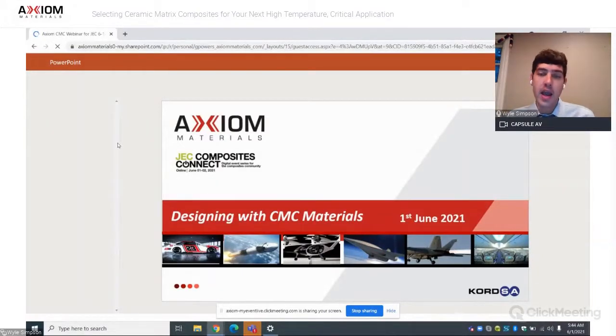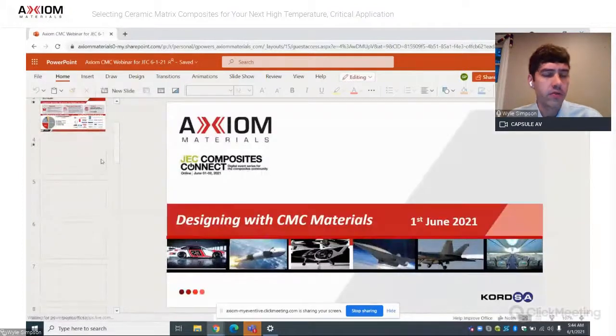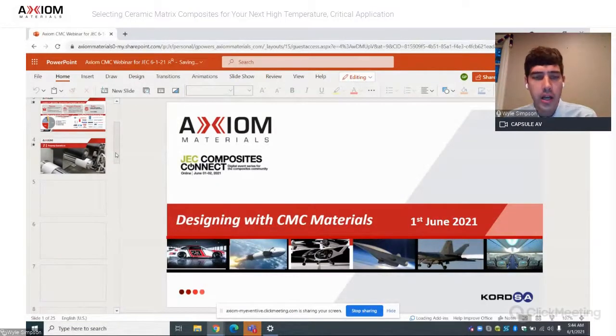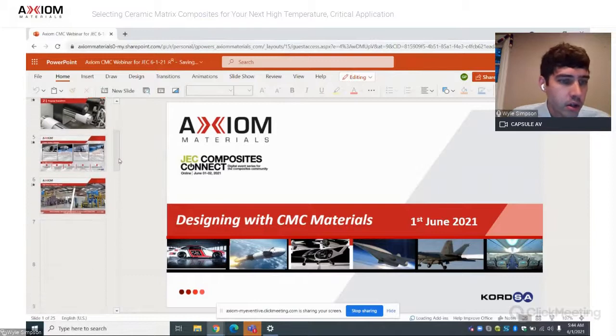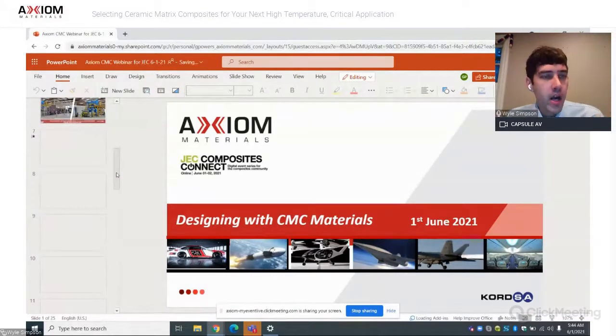But the 720 at those high temperatures, at use temperatures of around 2000 degrees Fahrenheit, you're going to see that the 610 and the 720 start to even out because of the resistance to creep that the 720 fiber has, that alumina-mullite fiber. That alumina-mullite fiber has a creep resistance mechanism in its grain structure. Grain pinning allows those grains not to grow so large that they're weakening the matrix or the fiber at those high temperatures.